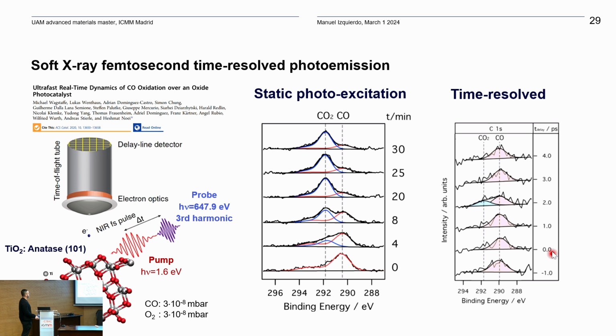Then what happens as a function of time is that around 2 picoseconds, you have a rapid formation of CO2. This CO2 is desorbed, and then your system is again with these adsorbed atoms, and you are ready for the next reaction. And this happens without the formation of an intermediate. Although the statistics is not amazing, you can see here that there are no extra peaks that show up.